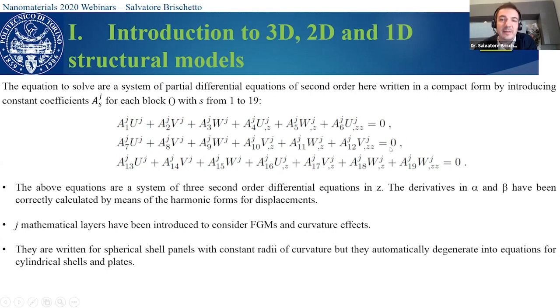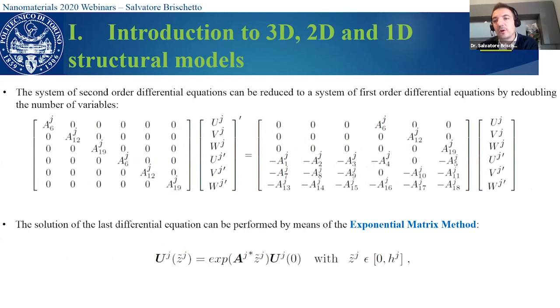In fact, we can note that some displacement components have the second derivative performed with respect to z coordinate. These terms are very, very complicated because they have inside several geometrical and material informations. And obviously, these partial differential equations are written for spherical shells, and they automatically degenerate in those for cylindrical shell panels and plates. In order to solve this equation, first of all, we reduce the order of the derivatives, so we obtain a system of first-order differential equations, and this is obtained by redoubling the number of variables.